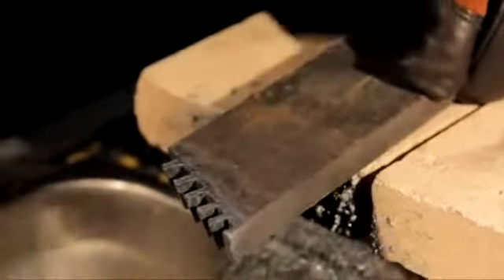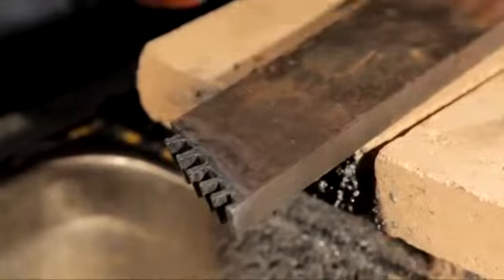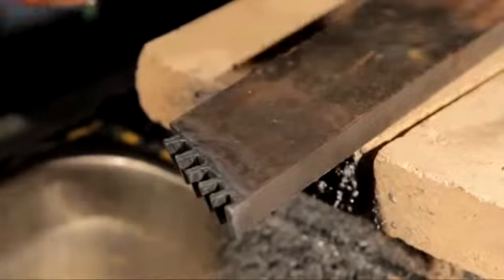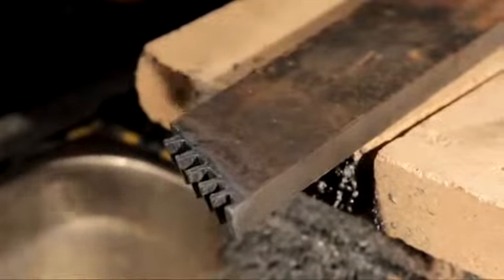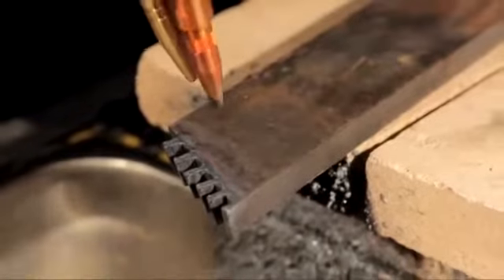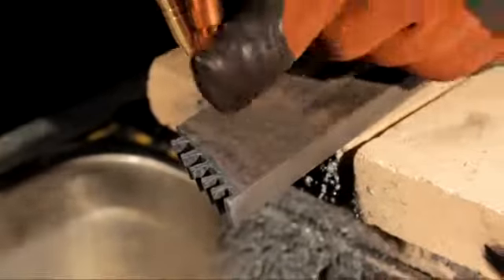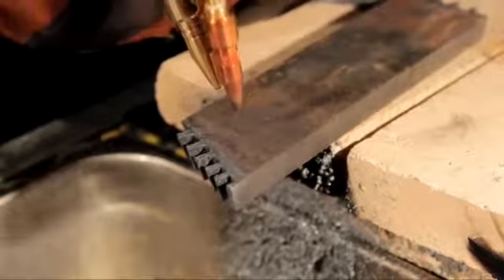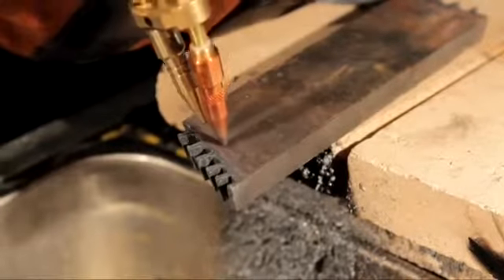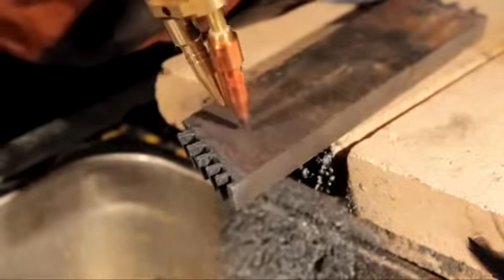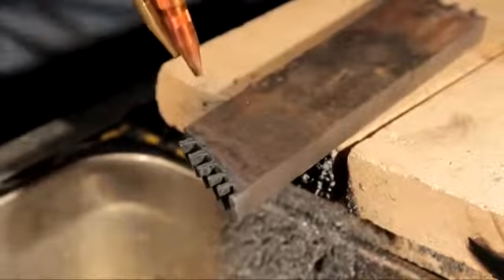Now, if you guys want to actually cut a hole in the middle of it, what you would do is get it red. You know, cut the heat up, real hot flame. Take that cutting tip. Once the metal is a little red and molten, pull that top tip a half inch up off the metal. Pull the trigger, blow the hole, then go down and cut just like you would with just a standard torch.